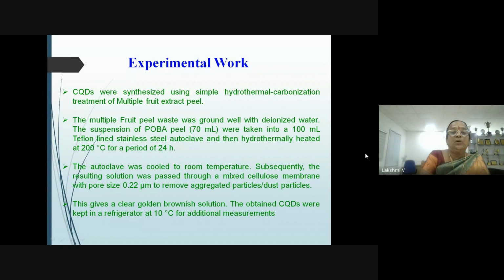In my experimental work, CQDs were synthesized using a simple hydrothermal carbonization treatment of multiple fruit extract peels. In the beginning, I started studying only with the banana peel, but then as my guide suggested, we used 4 fruit peels, that is pomegranate, orange, banana, and apple. The multiple fruit peel waste was ground well with deionized water.